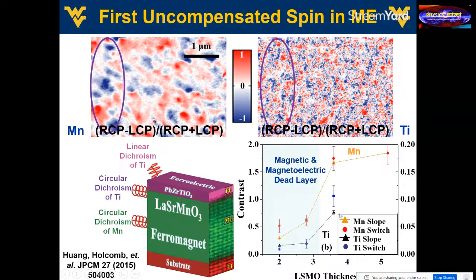So when magnetic films get thin, they lose their magnetism, in fact, faster than you would even expect, just based on normalizing for the volume loss. So that's called a magnetic dead layer. It's a confusing name, to be honest. We'll explore that a bit more. But when that happens, you also lose this magnetoelectric coupling. So that might not seem super surprising, but let's think about this. We're talking about coupling between a ferroelectric and a magnet.